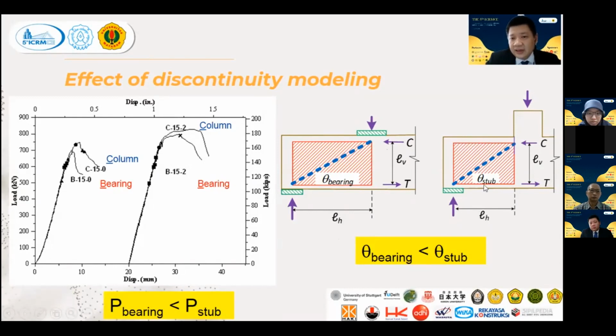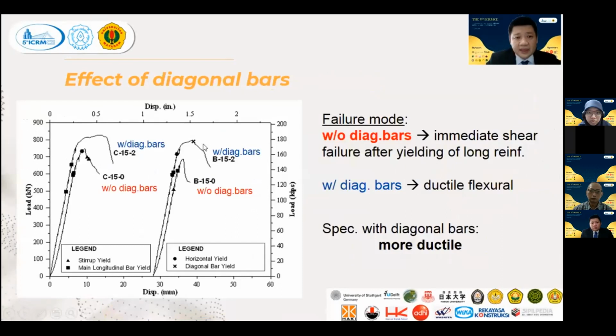Under the similar LV, your inclination angle of strut for specimens with column stub is higher than that of the bearing plate. Therefore, you have the higher load. Similarly, we can also observe for specimen with diagonal bars, although not so significant. For specimen with column stub, it also has a slightly higher load compared to the bearing plate. The reason why this is not so significant is because of the geometry; the failure is governed mainly by the flexure.